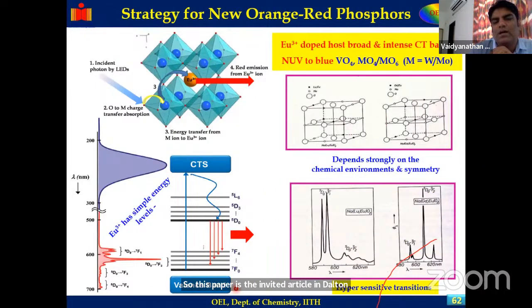As I told you, the absorption is due to the oxygen charge transfer band, and the emission comes from the europium 3+ ion. Europium 3+ has a simple energy level. When the europium ion is present at a centrosymmetric site, the magnetic dipole transition is dominant. When it comes to a non-centrosymmetric site, you get the electric dipole transition higher, which is called the hypersensitive transition.